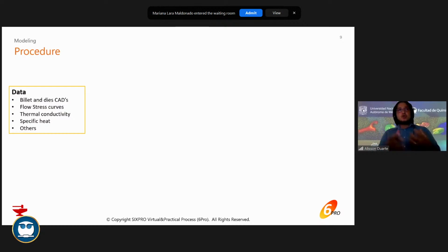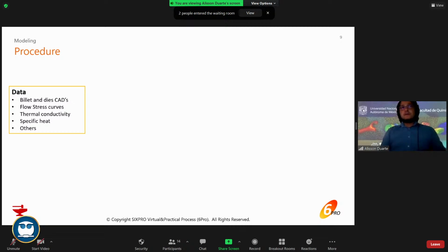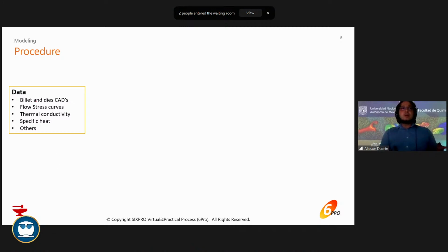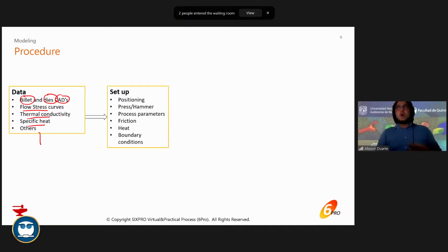Okay, in order to do this, we need some information. First, we need data for the material, and also the CADs for the initial billet and the dies, plus material data like flow stress, thermal conductivity, specific heat, and others. Once I have those data, I need to set up the simulation. So positioning is important. Which type of equipment, let's say a press or a hammer, which are my process parameters, temperatures, furnace, which type of friction, heating, and other boundary conditions that are possible to include in the setup.